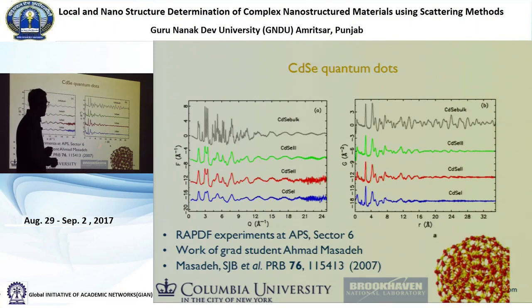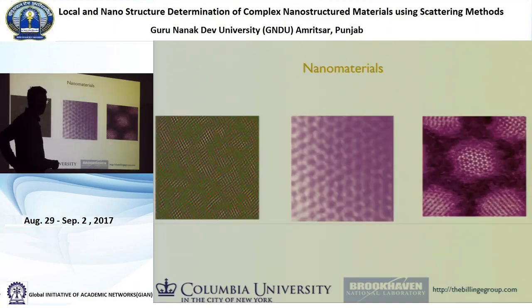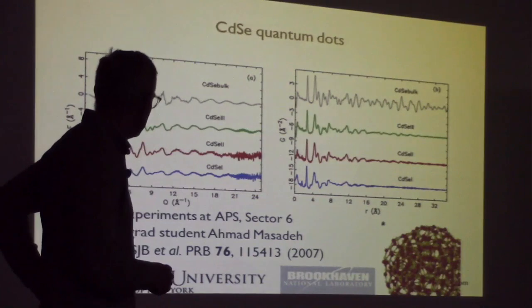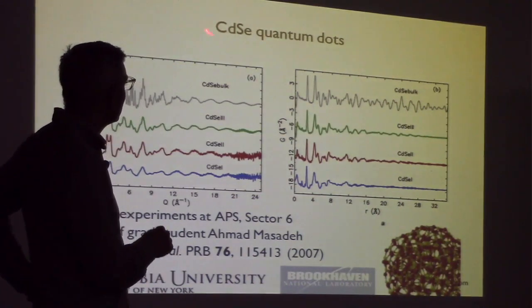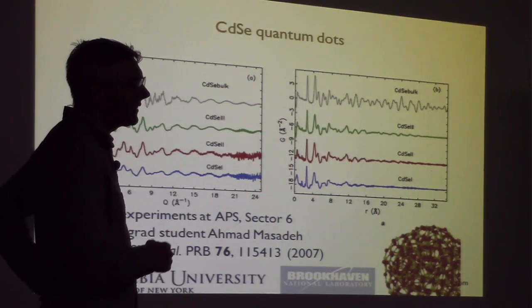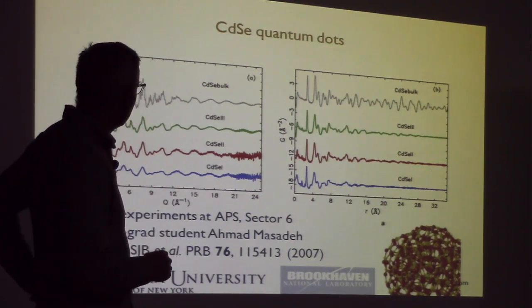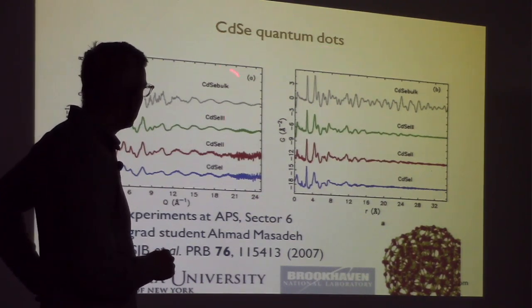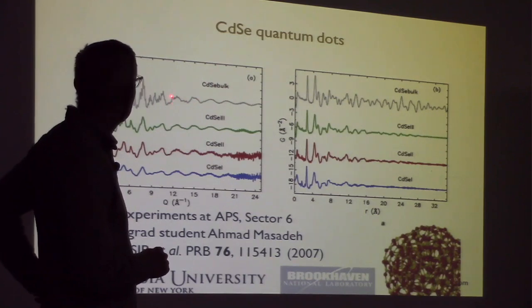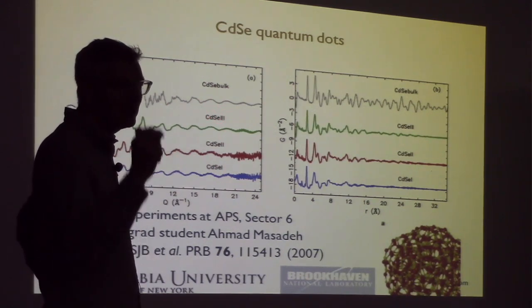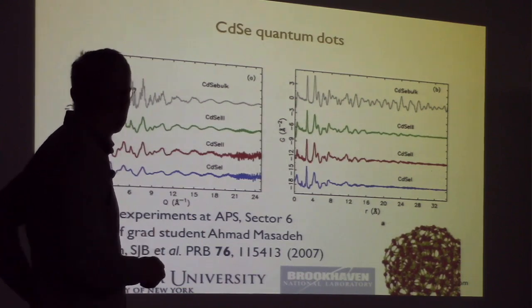So let me take you through this one example here of doing PDF on nanoparticles. So we're going to look at individual objects that look like this. It's cadmium selenide, which is a semiconducting quantum dot. I have three sizes, plus a bulk material, so it's cadmium selenide bulk. Then I have cadmium selenide 3, 2, and 1. And this is 4 nanometer diameter, 3 nanometer diameter, and 2 nanometer diameter. So these are different size nanoparticles.